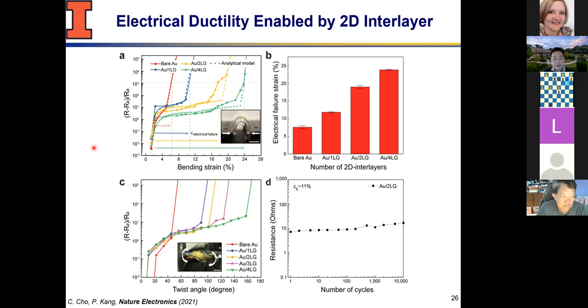So here are experimental data that shows the schematics I showed you earlier, resistance as a function of strain. Again, kind of bizarre to us at the very first measurement, but as you can see, this is about its original resistance, 10 to the zero, so that's one. And as you can see, with bare gold, no graphene layer, it shoots up very, very rapidly. And by having one layer, you start to see this plateauing region, and two layer and four layer. So it was quite interesting to see this, almost an elongation of this stable resistance.